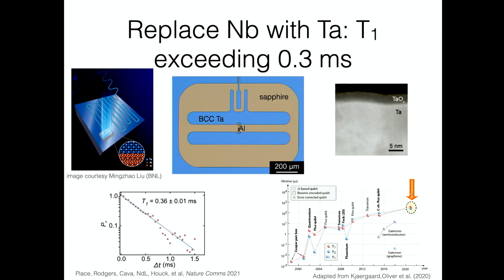And the punchline of this activity, so there was also a very large nanofabrication story on the back end, figuring out how to handle these materials, but we were able to sort of immediately get to qubit lifetimes exceeding 300 microseconds, which was a jump of about a factor of 3 or 4 over the state of the art. So we got to add our little improvement onto Schoelkopf's law plot here. So this was a nice big delta because we did one pretty simple materials science study, and we were able to improve on the global state of the art by a very large margin.